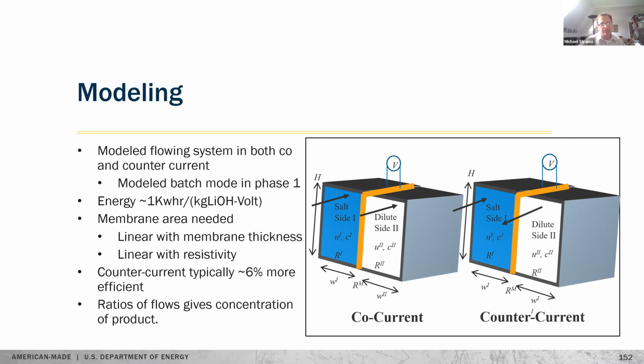So now let's go into continuous flow modeling. Consider 2 chambers separated by a membrane. What we want to do is set the flow rates between the brine and the product water. You can change the counter current by changing the direction, basically a minus sign. You set the input concentrations. You can calculate the chemical potential difference across it. You set how much lithium you want to extract. We said we want to go to 90%. And then the big question is, how much membrane do you need to do this? That's what the simulation goes for.